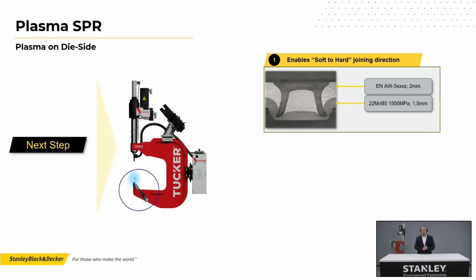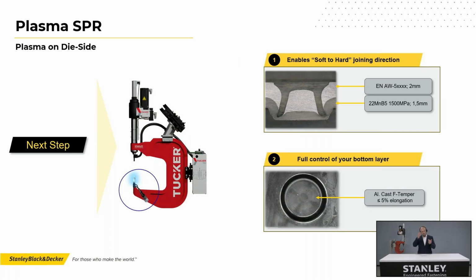So you can see a cross section on the right, where we joined aluminum into Usibor 1500 megapascal, and it worked fine. And the second benefit is that when you have the plasma on the die side, you can even more control your bottom layer. So we can use it on the top side or the bottom side, depending on where the more critical material is. Use it from the top and have some heat transferred to the bottom, or if your top is not a problem, but you have really low ductile, maybe recycled casting that looks like a puzzle and you can break it with your hands, maybe you have a really bad material, then you can try with plasma from the bottom, and then you get really nice results.